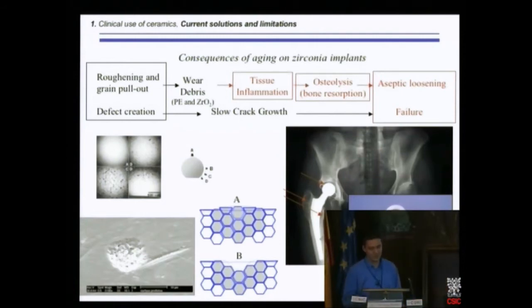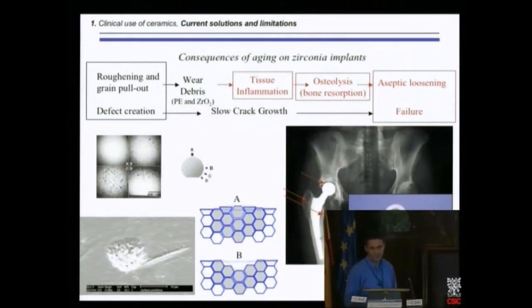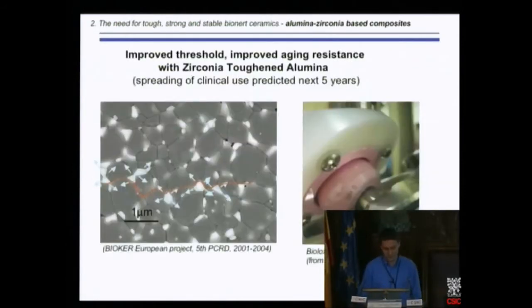Another important and maybe catastrophic issue is that you create a defect. A crater like that is a big defect, 10 microns or more in size. You have to remember that it's a large flaw, much larger than the grain size, for example. So this large flaw can propagate due to slow crack growth, and then you get delayed failure. That's what was the case, for example, of the Saint-Gobain Desmarquet prosthesis in 91 and 92. So defect creation means slow crack growth and risk of delayed failure.